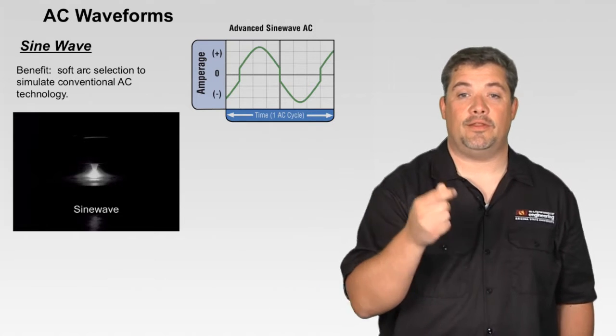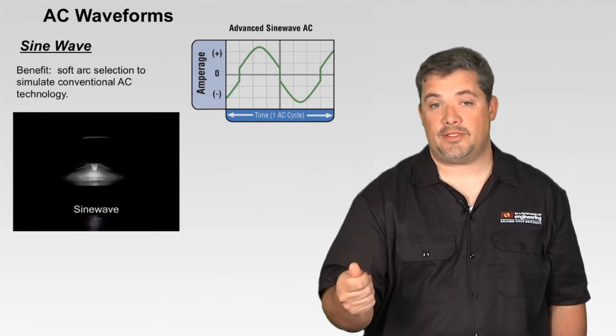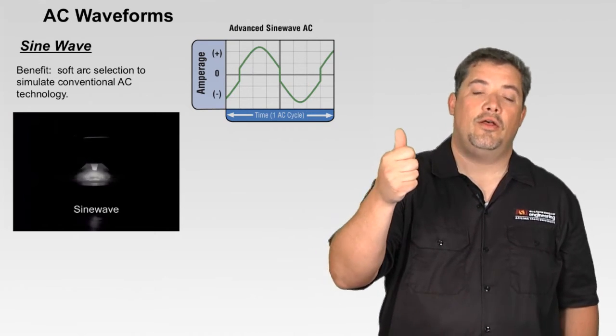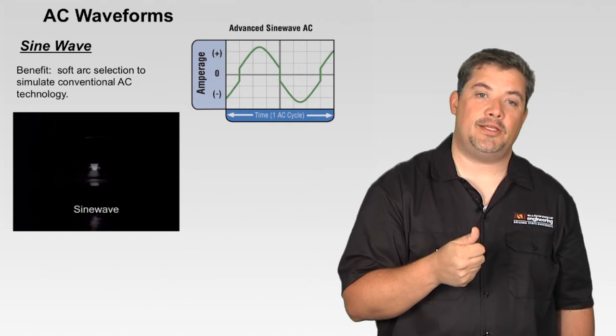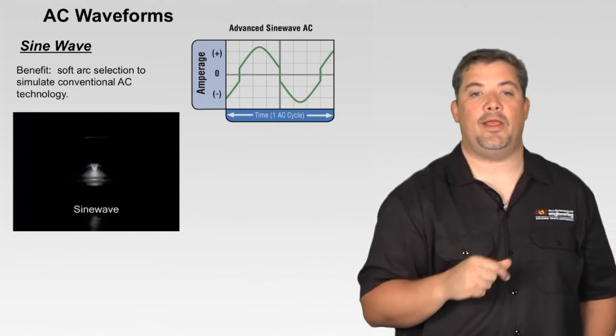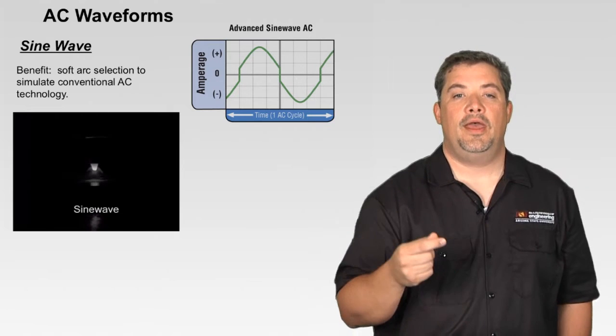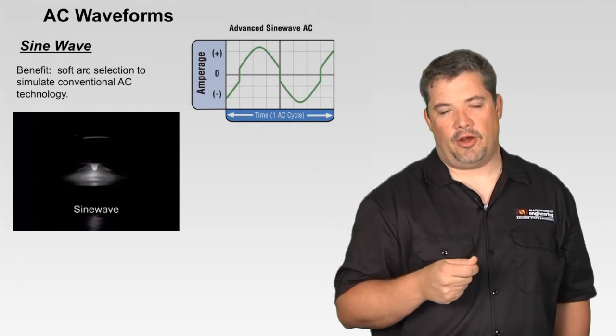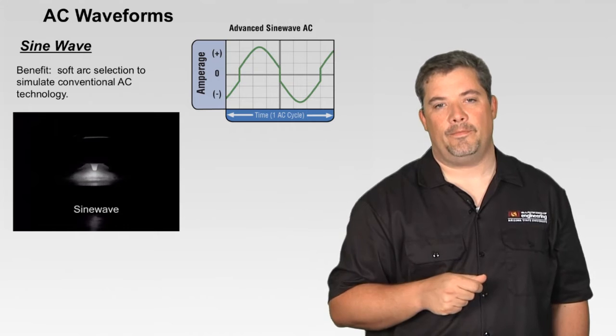So 70% of the time it's dwelling on the negative half of the cycle, and 30% of the time it's on the positive, which you can see by the etching happening on the surface, the little sparkles. And it's happening at 120 hertz, so it's on and off pretty quick.